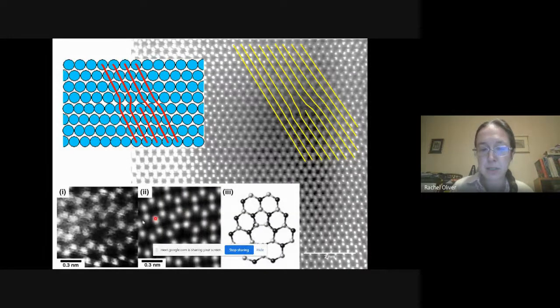If we zoom in on it in a bit more detail, you can take detailed images of the dislocation core. This is an actual image. The second one is a simulation of that image based on this structure here. And what we can see is that where the end of that missing half plane terminates, we have not the normal structure of 6-membered rings of atoms, but instead we have 5 and 7-membered rings of atoms. And that shows us how this dislocation distorts and alters the local bonding within the structure.